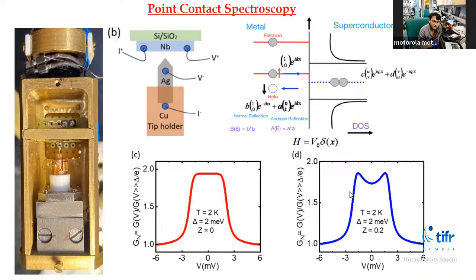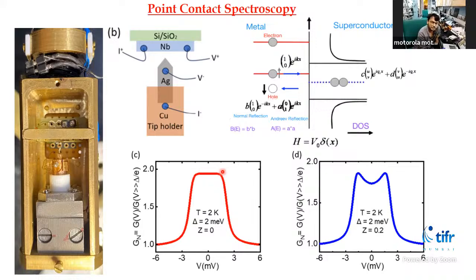But in general, it is very difficult to realize practically a junction which is very clean and get a doubling of the conductance plots. In practical purposes, we can't get a very transparent junction that can give us this kind of spectra. Due to some oxide layer on top of the sample, or some other effects such as multi-gap superconductivity, we practically get this kind of shape in our experimental spectra.